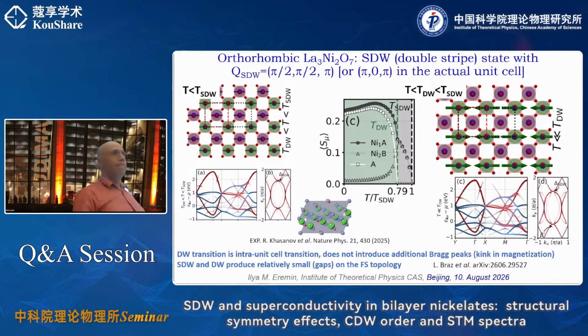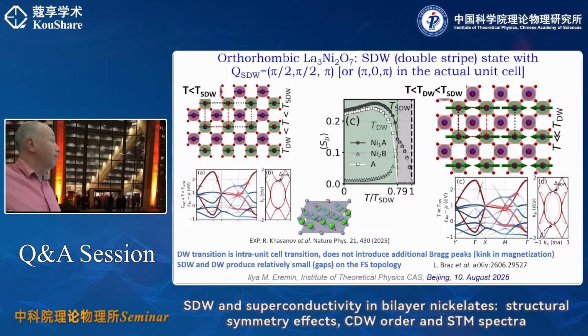Maybe I have a follow-up question. When you have this charge order, you see that one site has nearly vanishing magnetic moment. Well, very small, not exactly vanishing. Is this just because of the occupation of the d z squared orbital? What is the physical reason for this? Why does it become very small when you decrease the temperature?